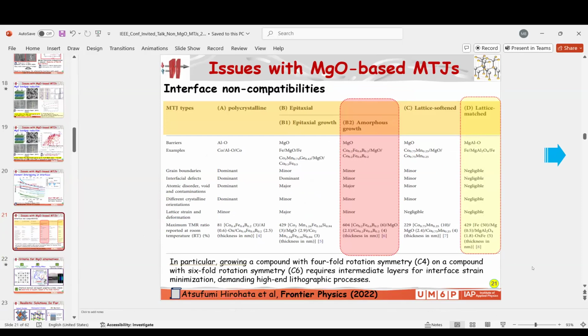So I'm going to present some of our results concerning the lattice match barriers plus other ones. Professor Hirohata here just made a great comparison, great job. All the defects, the shortcomings concerning grain boundaries, interface defects, atomic disorder, and so on, are minor somehow in epitaxial MgO, iron MgO, they are present or dominant. Minor in amorphous growth, and in lattice match, they are negligible.